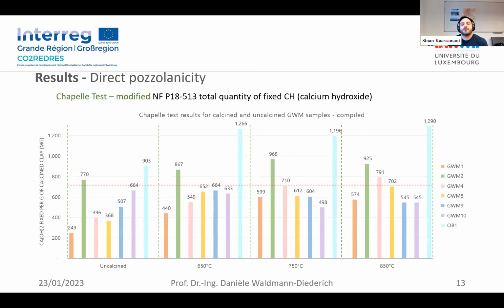So to move on, the Chapelle test, I'll just quickly explain it. We use the modified Chapelle test, so 2 grams of calcium oxide and 1 gram of SCM, the materials that we are studying, and then we measure the total amount of calcium hydroxide or Portlandite that's fixed by the solution. And then usually there's a line of around 700, the red line that we see here on the graph, and it's the usual value for metakaolins and calcined clays in general. Of course, the commercial ones can be much higher as well.